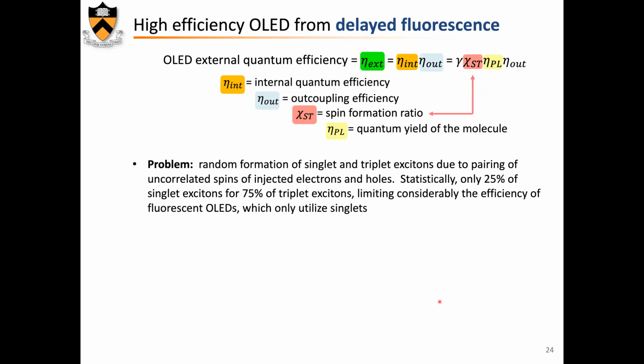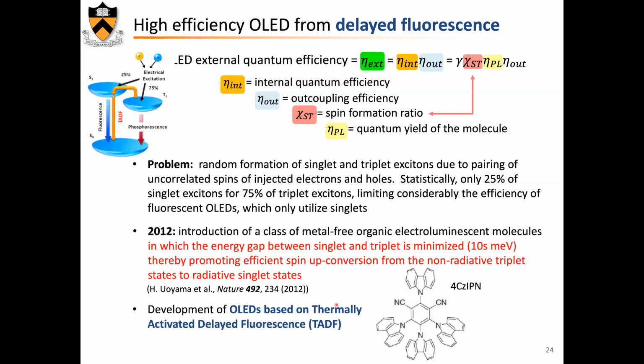Another very interesting fundamental development happened a bit later, 2010 or 12, that looked at the same problem of spin ratio. And that is the introduction of molecules. If we look at this picture here, this is the ground state S0, this is the singlet S1, and this is the triplet. These molecules were conceived and synthesized in order to have a triplet energy very close to the singlet energy. And that occurs when one of the criteria is that the wave functions corresponding to the HOMO and to the LUMO really do not overlap, or much at all, on the molecule.